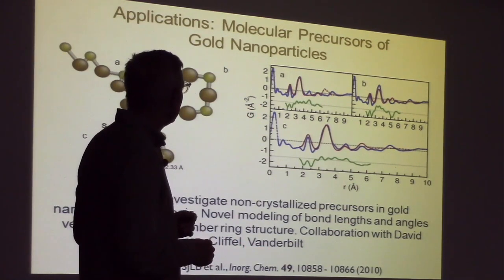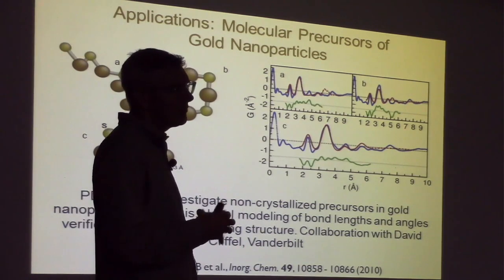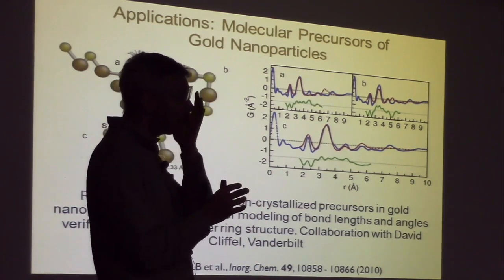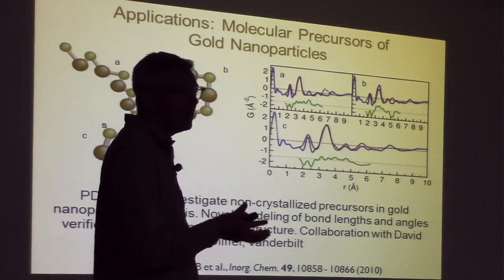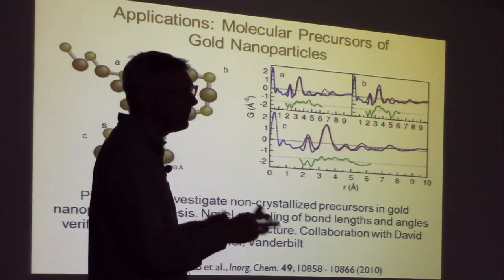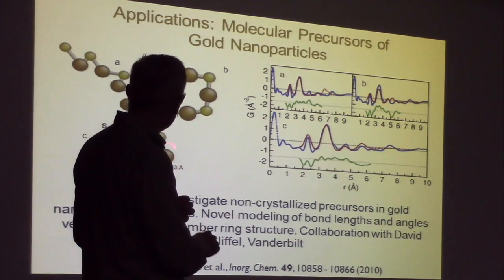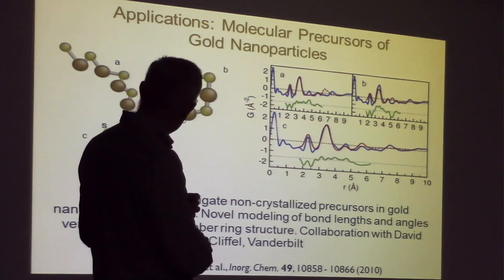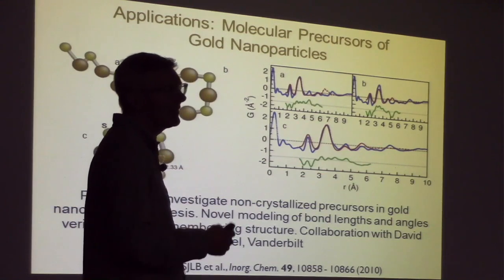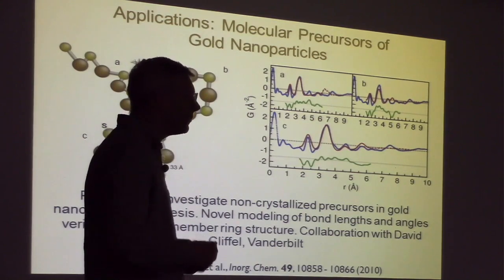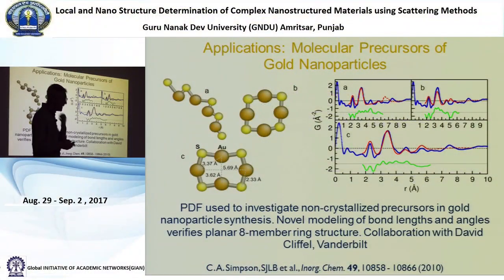For example, this was a collaboration with David Cliffel at Vanderbilt, and he's making gold nanoparticles in solution. And he actually wanted to look at, not the gold nanoparticle, the product, he wanted to look at what the precursor was. So you dissolve these reagents in the liquid, and what form do they take? Different possibilities are that they form these chains. Again, this is gold sulfur, gold sulfur, gold sulfur. So sulfur is really important in this gold chemistry. But then you could also have these kind of rings. And there's a very particular ring called an aurophilic ring, which looks like this. And actually what we could show is that this aurophilic ring is what the precursors look like in solution. Once you know this, you can start thinking about what reaction pathways are for the nanoparticle synthesis.